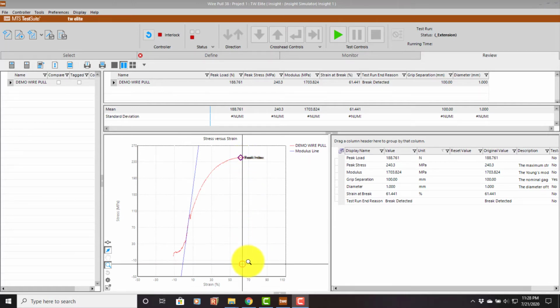Now remember, on the annealed samples, they're all different diameters. So when you put in the next test pull, you need to make sure that the diameter up here is set to the correct diameter. So on each test, you got to put in the 0.9, the 0.8, the 0.7. And simply enough, when you pull the samples from the oven, just use the calipers on them to determine what the diameter is. It's that simple, because they'll be all jumbled up if you're going to cook them all at once. But you do that, and you'll have all your curves for this experiment, and it'll look great.